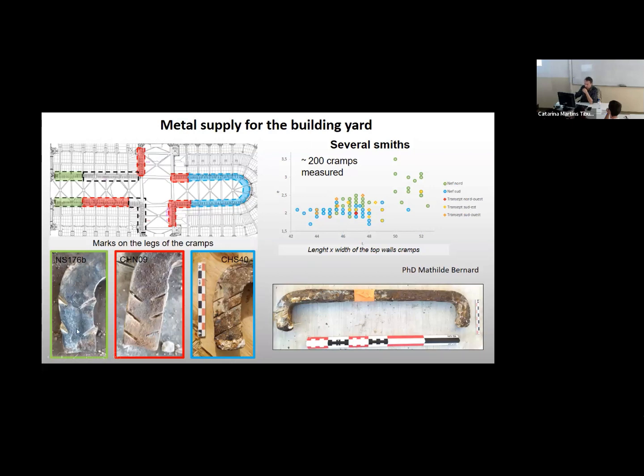And so what we could see is that there were notably different workshops, different smiths that worked on these iron cramps, because they shaped the cramps in different ways and sizes. You see here in Nave North, there's a group which is bigger than the other cramps. And when you look at the tip of the cramps here, you have some marks that are made to attach the cramp better in the stone when you pour some lead. I should say that most of these cramps were sealed with lead in the stone, so that the iron cramps would better attach the lead when it's being poured into the cavities that are carved in stone.